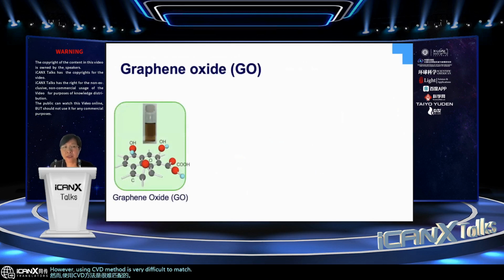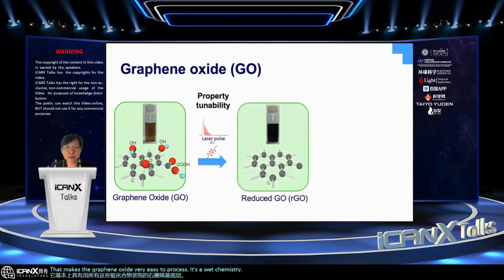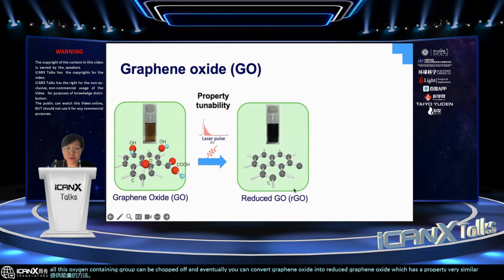So in our laboratory, we developed a completely different route. Basically, we start from graphene oxide. The reason is that graphene oxide is water soluble. It basically has the graphene basal layer decorated with oxygen-containing groups, which makes graphene oxide very easy to process. It can be synthesized by wet chemistry. Then by using laser pulses or some other method to provide the energy, all these oxygen-containing groups can be chopped off, and eventually you can convert graphene oxide into reduced graphene oxide, which has properties very similar to pristine graphene.